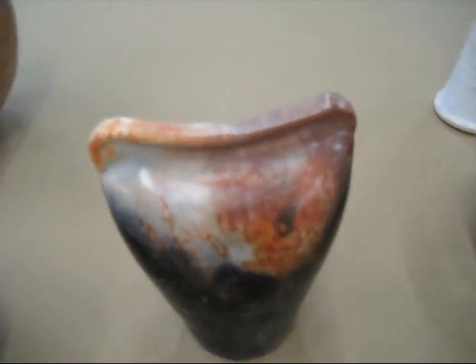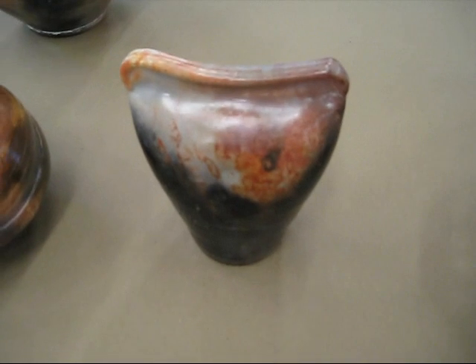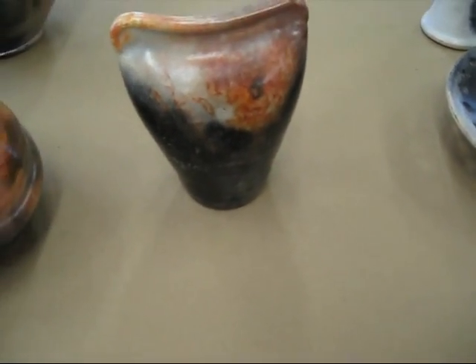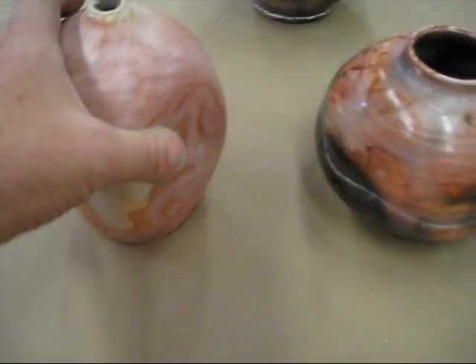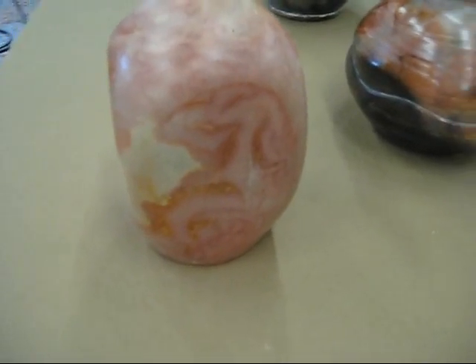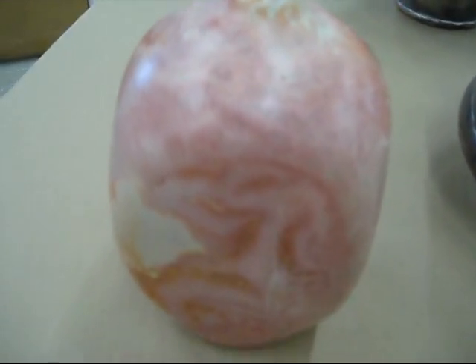This one here is my red clay with a white slip over it. Then I put the SIG on it, buffed it, and then treated it the same as the others — with ferric chloride and wrapped in aluminum foil. This one had no seaweed in it, just the ferric chloride and the salt. As you can see, all the whimsical patterns inside the aluminum foil — that's what was created. It's a really beautiful pot, it's a shame it's just not smooth enough to show a lot more detail when waxed.